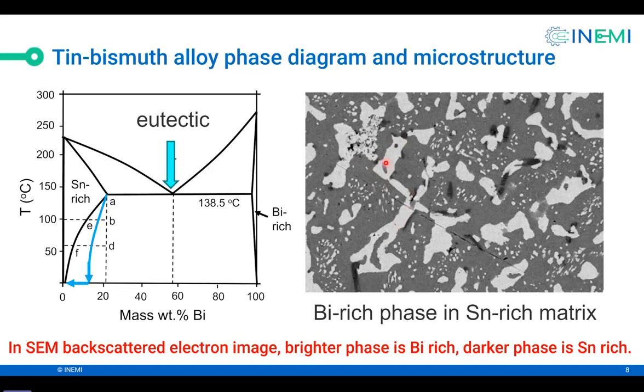So bright area is mostly bismuth and a very small amount of tin dissolved in it. The gray area is tin, which has up to about 21% bismuth dissolved in it, just below eutectic. So just below eutectic, you get this large bismuth eutectic structure. Now, when you cool to room temperature, cooling in air is not under equilibrium condition. So you essentially follow this blue line and you get to a structure that is not equilibrium.